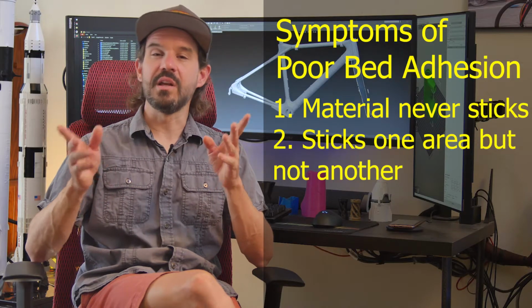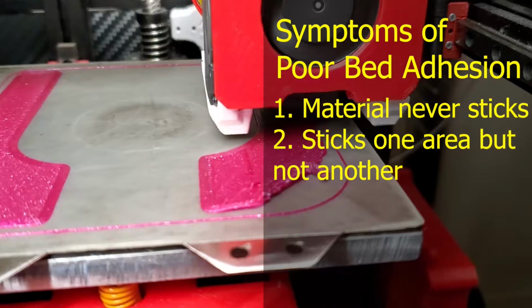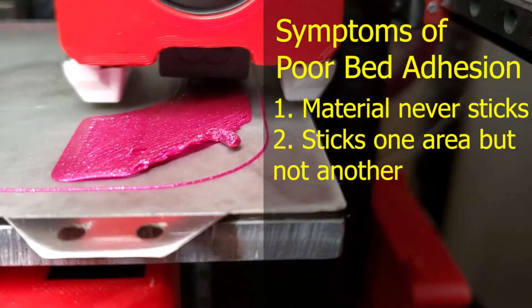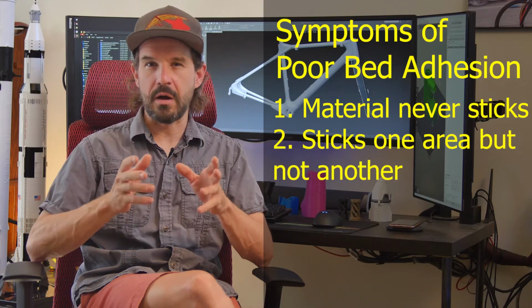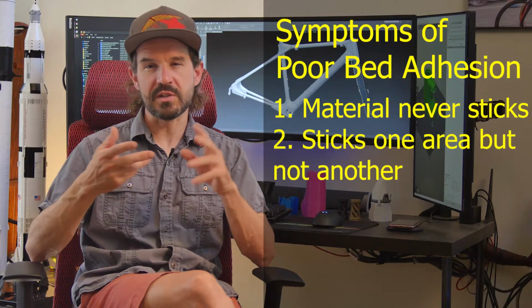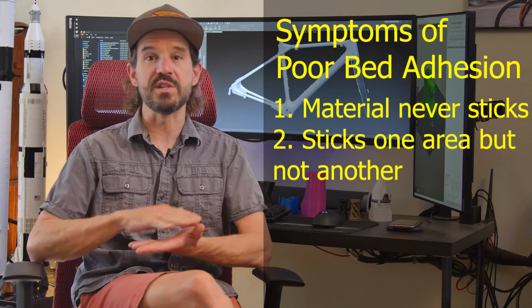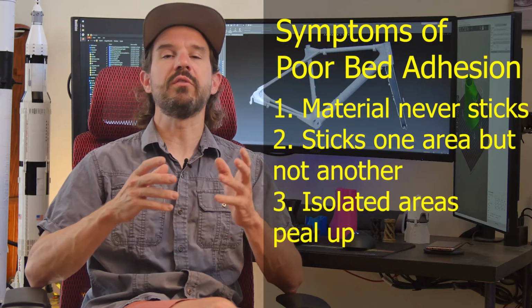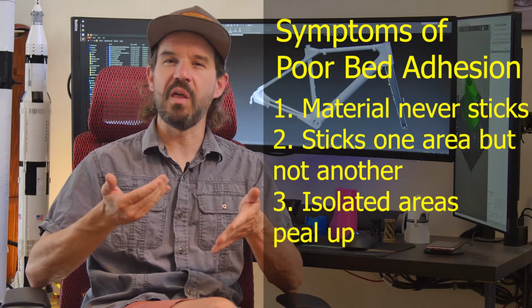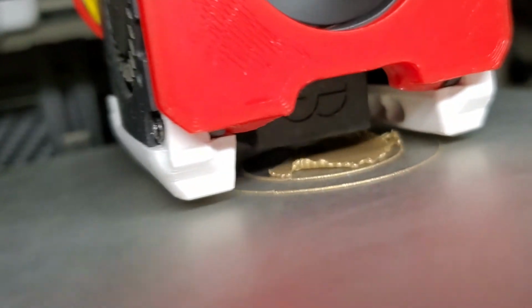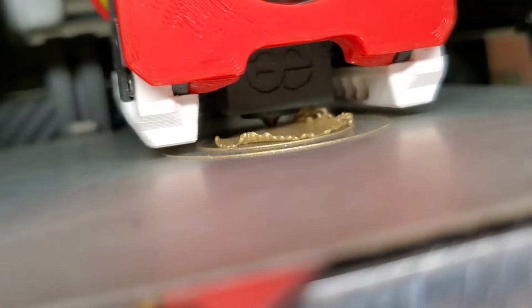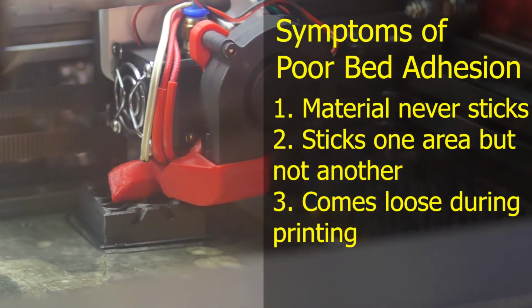The material sticks in one area of the print bed, but not in another. This is a common symptom I've seen with PEI sheets that are starting to wear out, and it's a sign that you need to stop your print and clean or resurface the sheet. Parts of the first layer start to peel up, especially noticeable in sharp 90 degree corners or in areas of the brim, if you're using a brim. Or the part just comes loose during printing.